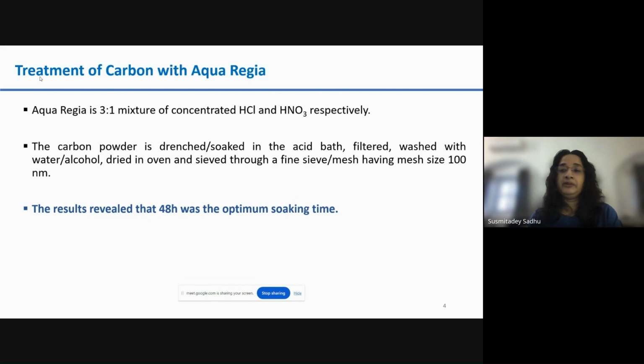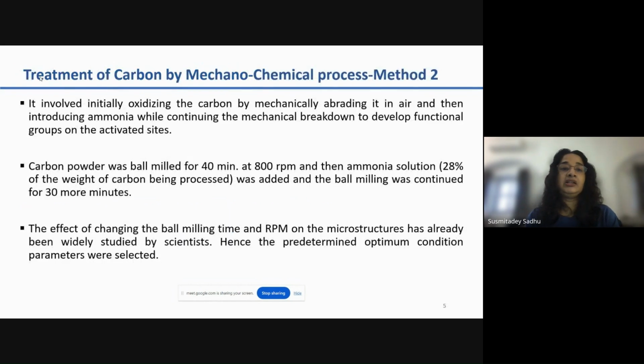so that we get a fine powder. The second method of carbon black treatment is a mechanochemical process, in which we have ball milled the sample for 40 minutes at 800 RPM, and then it is treated with ammonia solution and again ball milled for another 30 minutes so that the surface area is increased along with introduction of some active groups.